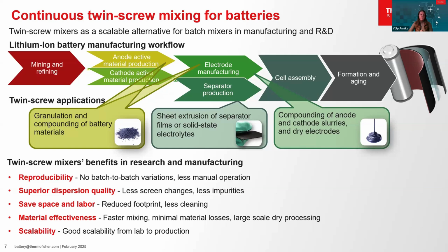Material effectiveness is enhanced. The mixing process is significantly faster with twin screw mixers, completing the task in minutes rather than hours. Continuous processing then minimizes the material losses, making the process more efficient. Twin screw mixers are also effective for large-scale dry processing, which we talk about later. Twin screw mixers provide good scalability due to the large surface to volume ratio in the mixer, making it easy to transition from lab scale experiments to full production. High material and time consumption at manufacturing scale create the need for lab-scale twin screw mixers for advancing battery R&D. A downscaled solution is presented now on the following slide.